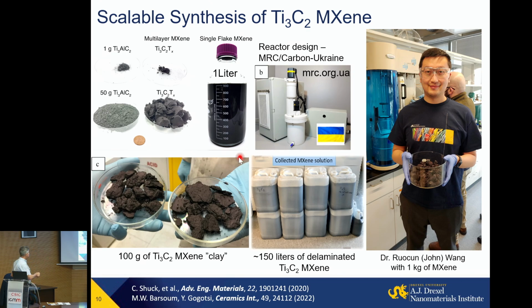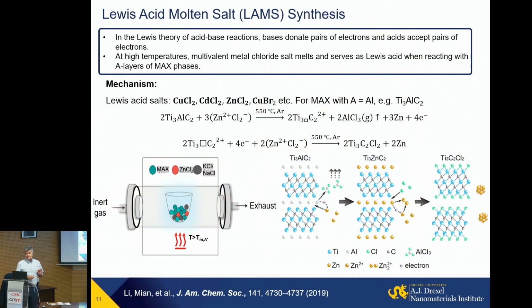So in this process, we start with ceramic powder. We dump it in solution, make this MXene clay, and we disperse it in water, again, without any binder or surfactants. So this is a wet chemical method, and it has advantages because we get a colloidal dispersion of two-dimensional particles in water with no surfactant needed, unlike, say, metal ink or graphene, and right away it will be conducting. But if you want to make materials which are uniformly terminated by halogens, materials that can after that be much easier functionalized chemically, you may wish to use different methods.